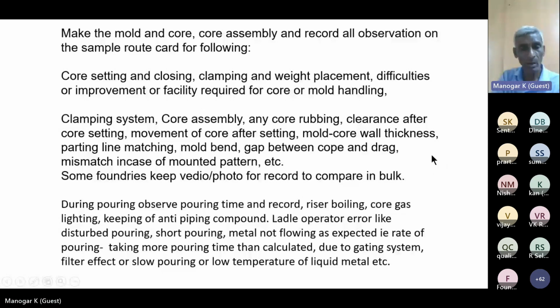So during pouring, record the temperature, pouring time, temperature in the furnace, temperature in the ladle, and the lighting up of the gases and providing the anti-piping. But anti-piping compound, people are not simply putting some amount, but as per the supplier, you have to weigh it and keep the packets and put it properly, not just simply putting by your spoon. So this one point is missing in many of the foundries which I visited.